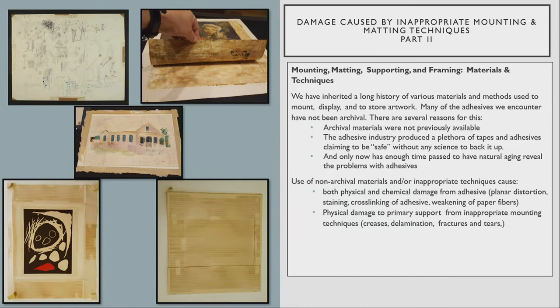So you can see on the top left, in the left image, which seems a little blurry, but maybe that's because I'm looking at a weird angle, there's pressure sensitive tape, and then on top of that, masking tape. On the right, this was glued with rubber cement. And you can see both the staining, that's oxidation, of the paper it was supported to and the artifact. This watercolor was glued to a backing board and then on top of that, masking tape.